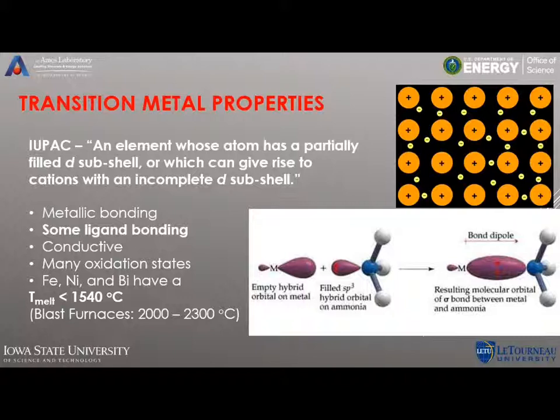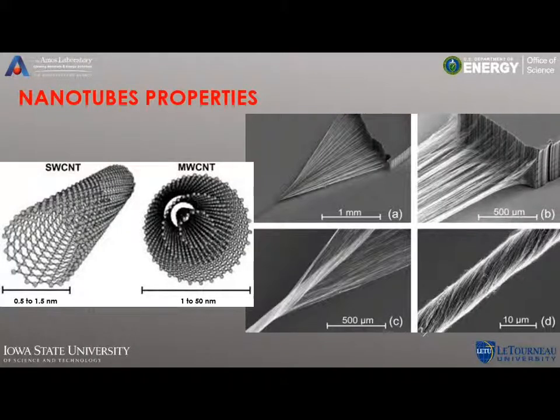You can say, take the example of iron and purifying it and refining it from iron into steel with a blast furnace. Now those blast furnaces are highly inefficient because you have a lot of heat that escapes and is lost, and so that energy is not being used to reduce the metal oxides. In this case, we were looking at the first summer, this is back in 2013, reducing these metal oxides to their pure metals with the maximum possible energy efficiency. And that was by the microwave reduction, which I'll go into a little bit more in a moment.